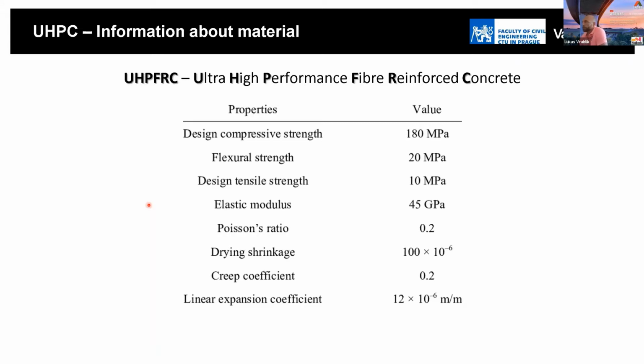Again, it is very important for the design, because you only have to think about the shrinkage during the preparation of the casting of the element. But if you put the precast element into the final statical scheme, into the final structure, you can neglect the effect of the shrinkage. So again, very important and very interesting compared to normal concrete, where shrinkage and creep could be a problem. With UHPC, we don't have a problem with these two phenomena of the behavior of the concrete.